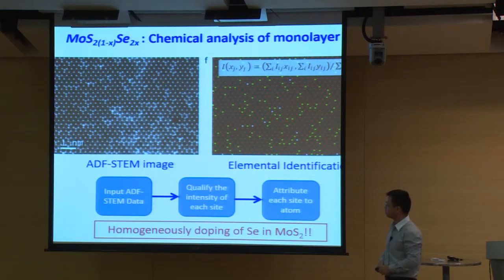So from our observation in the microscopy, we have looked at a lot of places. So no separation in these materials. So selenium is homogeneously doped in this moly disulfide lattice. So this is really interesting. We never saw this for the BCN system.